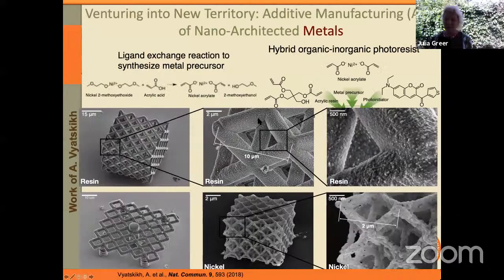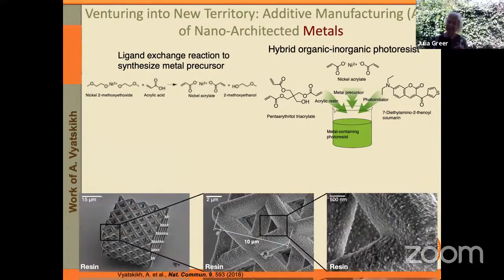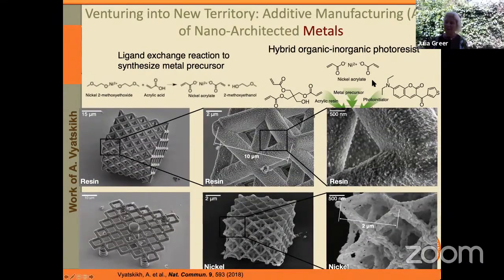Now, as we're looking at this architecture, the unit cell size here is about 10 microns, and each beam might be about 2 microns in diameter. This particular resin contains both the nickel and the organic material. So how do we get rid of the organic material? Because ultimately what we want, of course, is the nickel. Well, one way to do it is by burning it. Undergoing this process called pyrolysis, we can burn off the organics and end up with an entirely nickel microstructure.